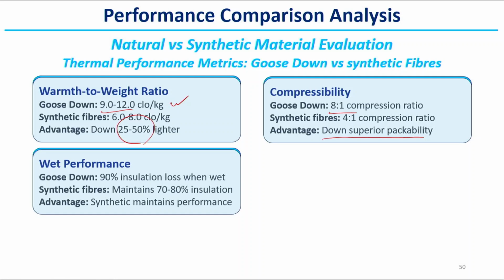So, wet performance is not very good in case of goose down, but synthetic maintains 70 to 80% insulation, only 20 to 30% insulation is lost, but in goose down only 10% insulation is kept, only 10%, 90% is lost. So, synthetic material performs better.